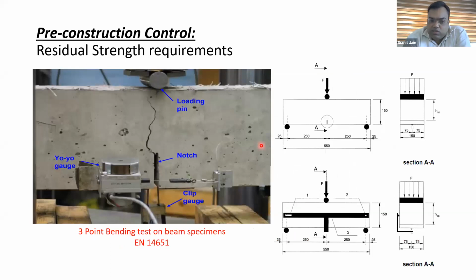Now this is the same as the 4-point bending. There is another test called the 3-point bending test. This is also carried out on a beam specimen. And here we are actually measuring the mouth opening displacement. There is a notch which we are creating in the specimen, and we are tying a clip gauge to that notch. This clip gauge measures the opening of the crack or opening of the notch as the loading is coming from the top.